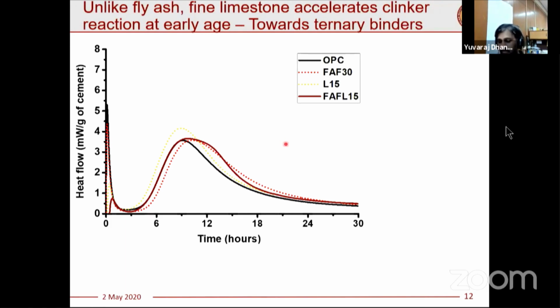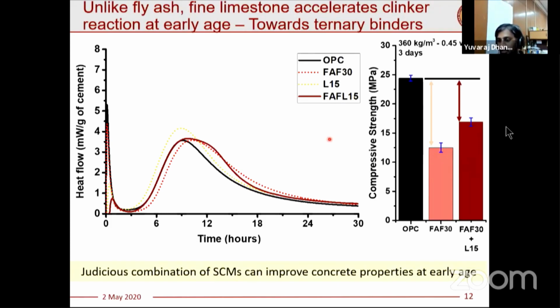And when you do a very simple assessment of compressive strength of concrete, you can see this is for the OPC. When you go for a fly ash concrete, early strengths are much lower, and we obviously know that it will pick up in due course of time. When you go for an additional replacement of clinker by means of limestone, 15% limestone, the strength difference, which is about 10 megapascal at 3 days, can be brought down to nearly 5 to 6 megapascal. So we need to have a judicious combination of SCMs, which can improve the concrete performance at the early ages. And we have also made an assessment of the later age strength, which doesn't seem to be much different.